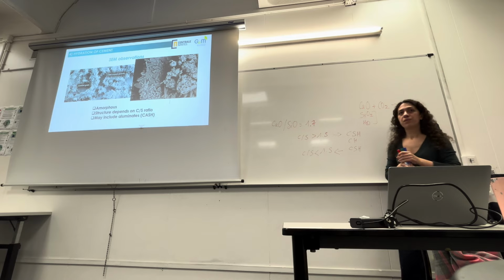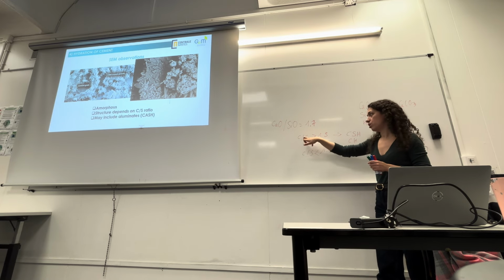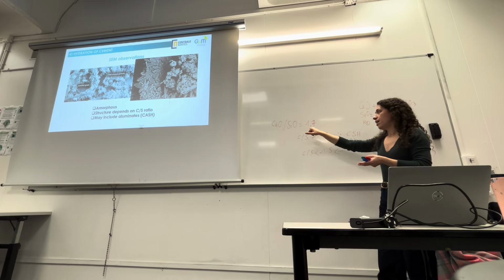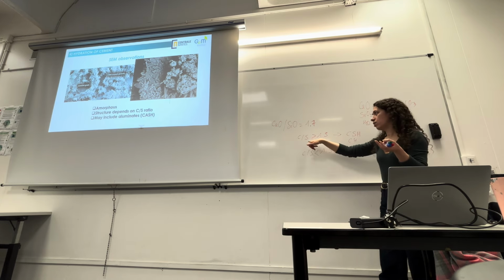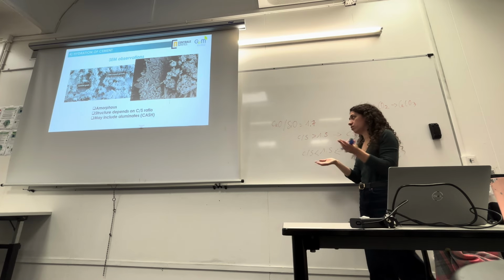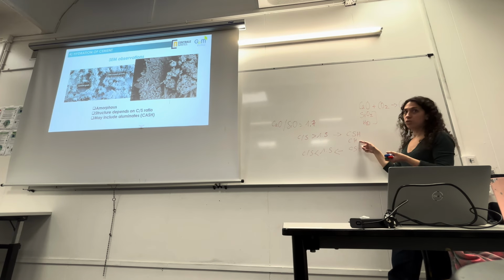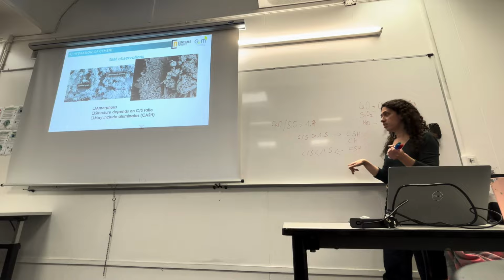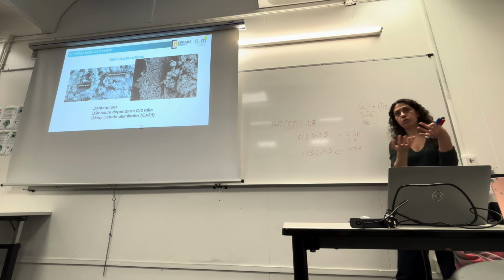Can you explain that again? If C over S is bigger than 1.5, that means you have too much calcium oxide. Once you consume all your silicate, calcium oxide will still be here. This calcium oxide will not react with silicium, because silicium is eliminated. It will react with water and form also CH. But if your calcium oxide to silicium oxide ratio is lower than 1.5, you will consume all your calcium oxide with the silicate from CSH. You won't get any residual calcium oxide to react only with water.